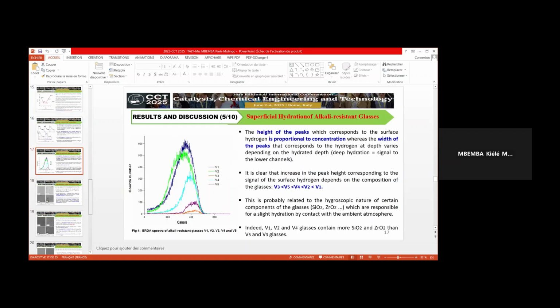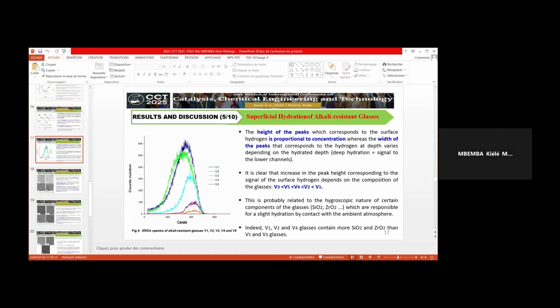Concerning superficial hydration of alkali-resistant glasses, we can see that V3 and V5 are less hydrated glasses compared to V4, V2, and V1. This is probably related to the hygroscopic nature of certain components of the glasses, like silicon oxide or zirconium oxide, which are responsible for hydration by contact with the ambient atmosphere.